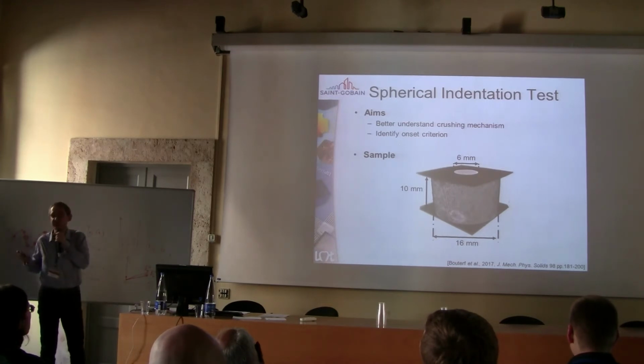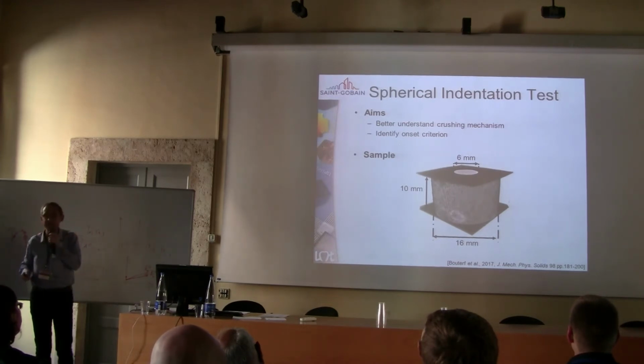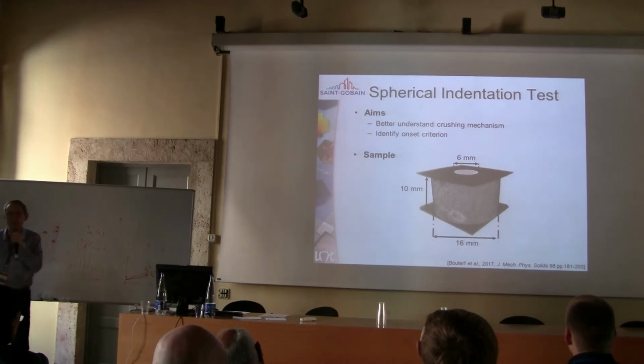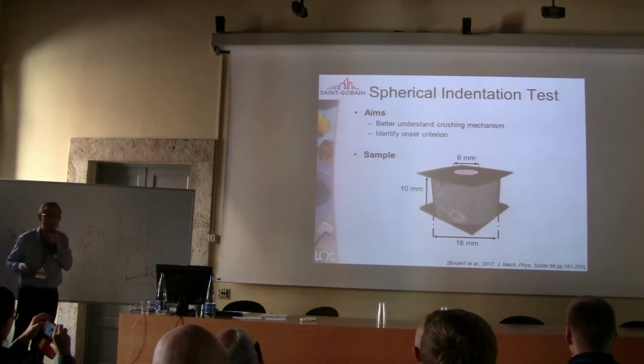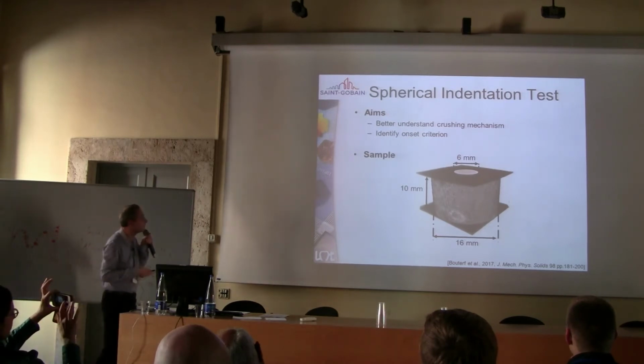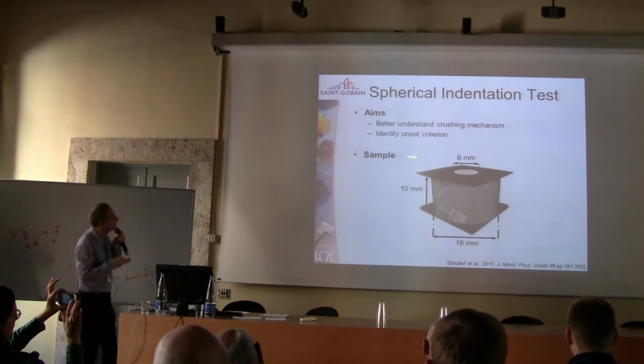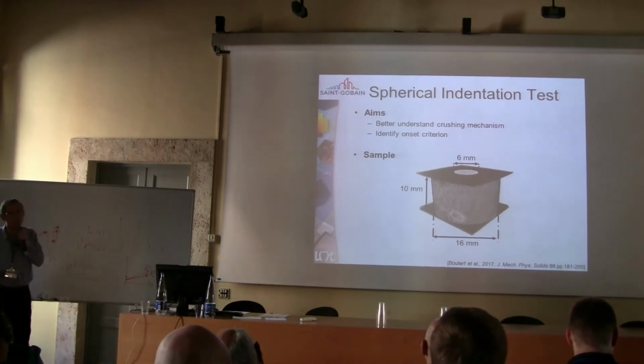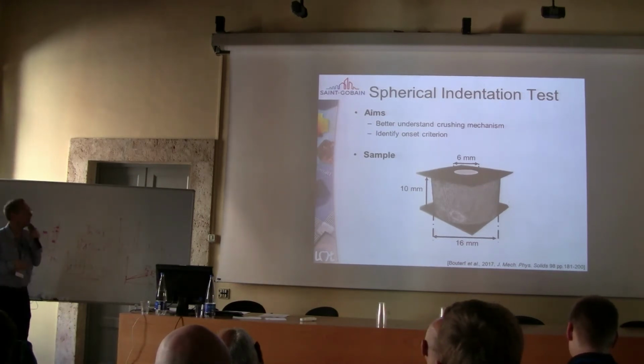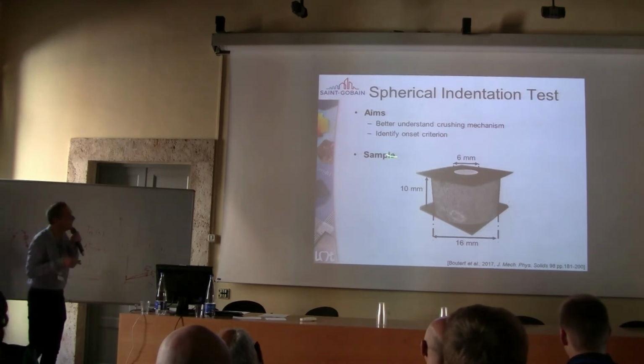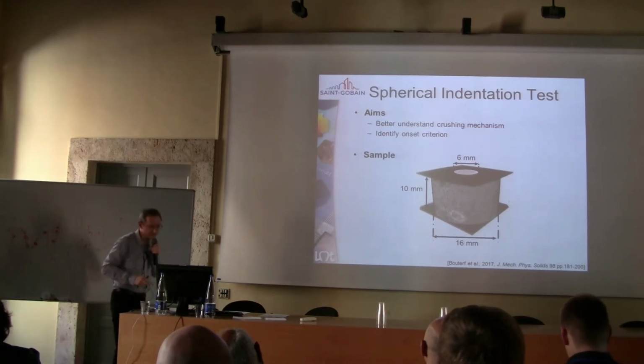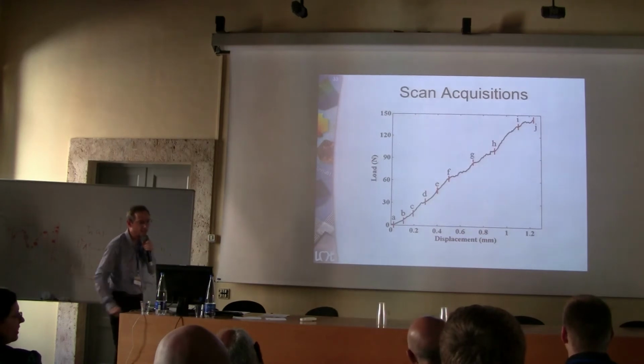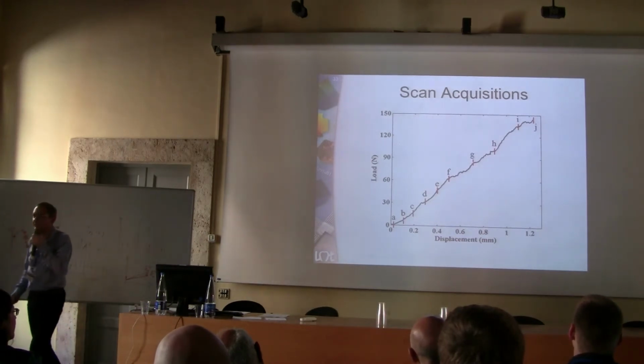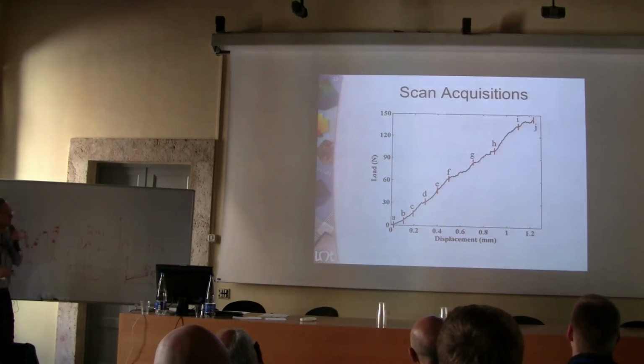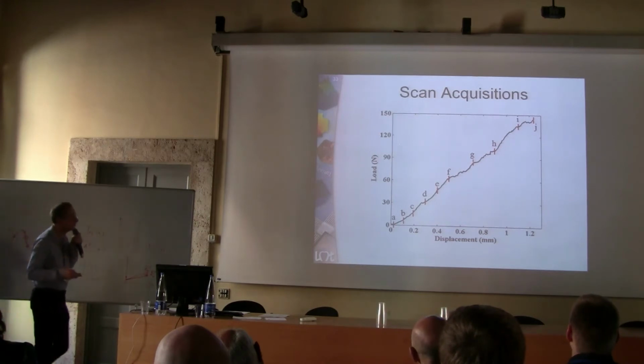One typical experiment to mimic that is to perform indentation tests. In indentation tests, basically all the action is taking place under the indenter, which is something you don't have access to except if you use 3D imaging techniques. As you will see, we were after the crushing mechanism that occurs under the indenter and possibly identify an onset criterion.